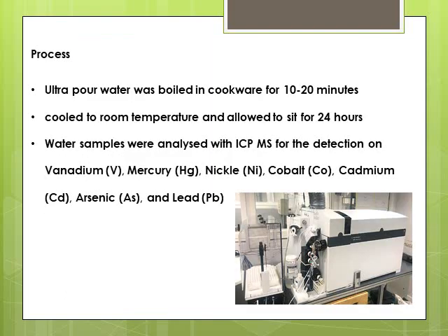Now the process of how we test them is that we take ultra pure water, put it in these cookwares, and let it boil for 10 to 20 minutes. Then we let the water cool down and sit inside the pot, these materials, the stainless steel, whatever, over 24 hours. The water sample is then collected, processed, and made ready to be analyzed by ICP-MS. And we look for the amount of, again, vanadium, mercury, nickel, cobalt, cadmium, arsenic, and lead in each sample.